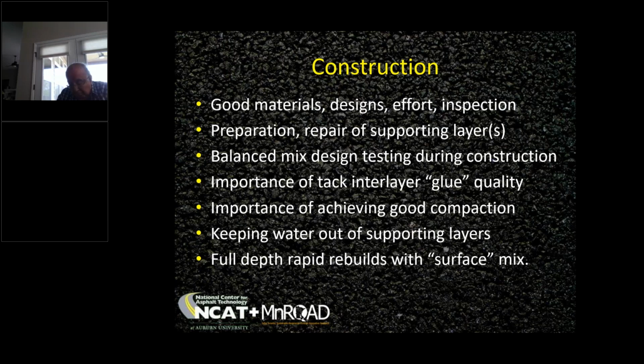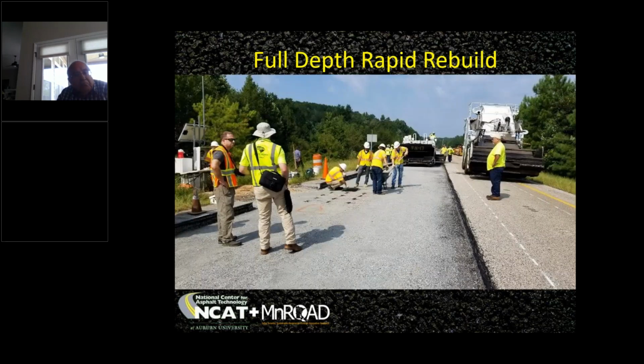And if we do it, what kind of smoothness are we going to get, and what kind of density profile are we going to get? So for this experiment, we did 3 different test sections with between 7 and 8 inches of mat placement, and this was 12.5 millimeter nominal maximum aggregate size surface mix that we did in a single pass, compacted 8 inches in a single lift, and we cut our cores, did density profiles.